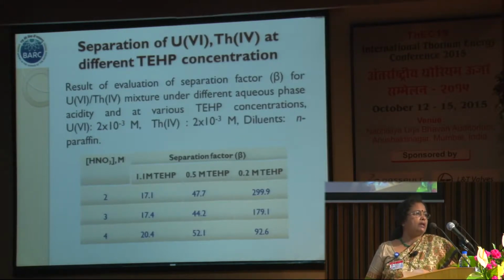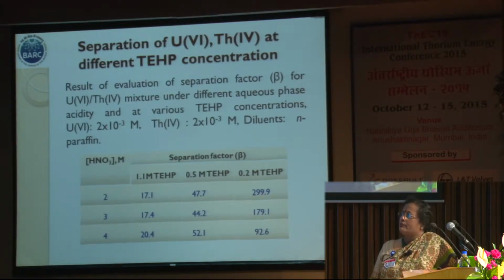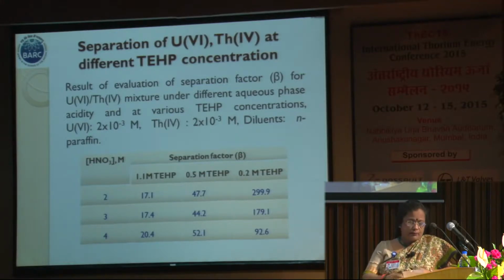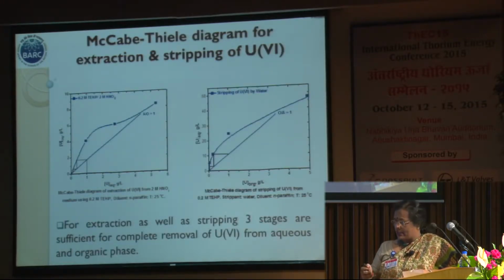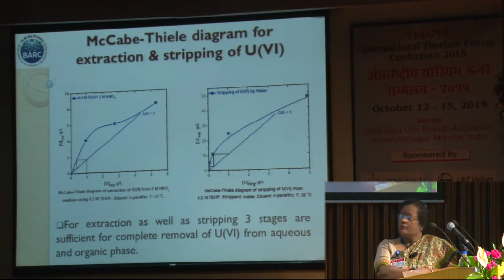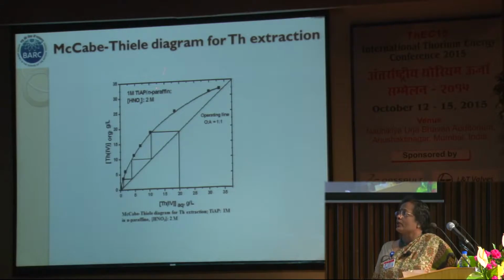This is very important for us because when you use enriched uranium, your uranium recovery should be very high. Additionally, we checked how it changes with the molarity of the nitric acid and with the concentration of the extractant. We have seen that if you dilute the extractant, for this dilute solution, whereas our range was around 1 GPL, you get a very good separation factor. Based on that, as we have to do the engineering for recovery systems, we did our McCabe-Thiele diagram construction. We have seen 3 stages were sufficient in this range. So if you put in your stage efficiencies, it will come to a reasonable number. For thorium also, we have tried with triamyl phosphate, where we could see that we are able to take it back within 4 stages.